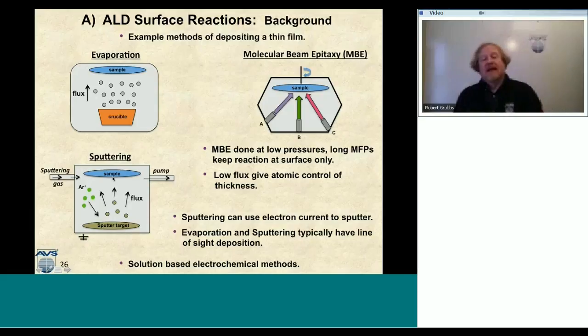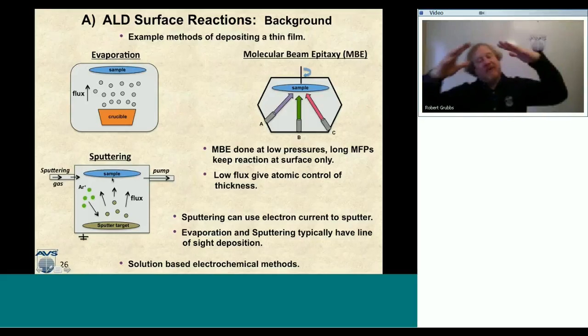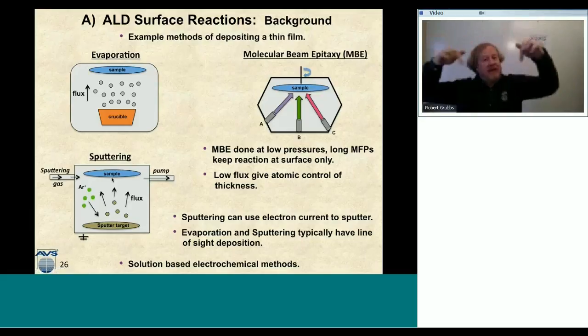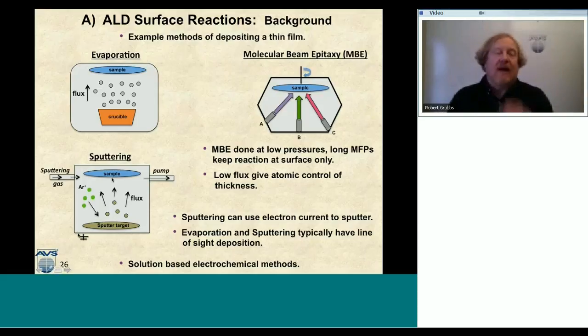We can use argon atoms and negatively bias the sputter target, or this also is done with electrons, where we have an electron beam and we positively bias the sputter target and accelerate electrons into the sputter target, and that ejects the material from the sputter target and then deposits on the sample. Again, this is a line of sight deposition technique, but there are very exotic ways of taking your samples and mounting them at angles and rotating and spinning them so that you get better uniformity, and maybe coating some trench-like structures if they're not too big.